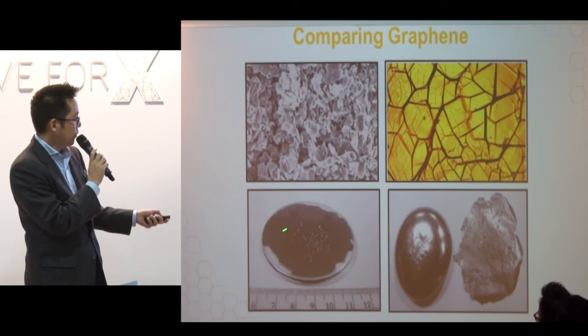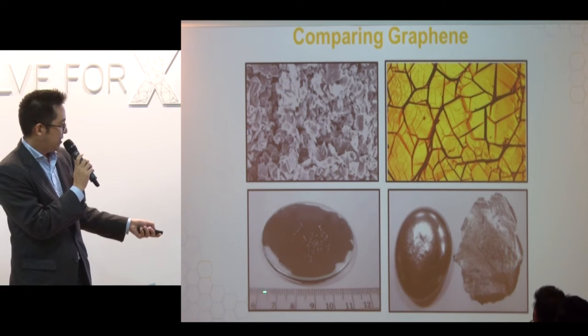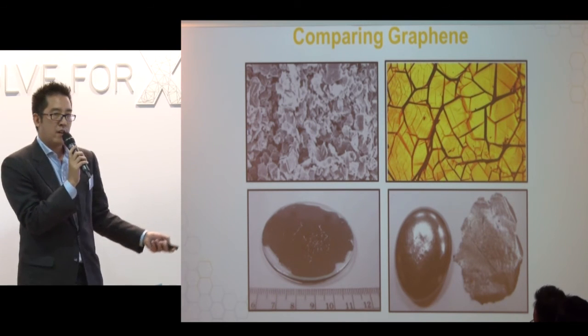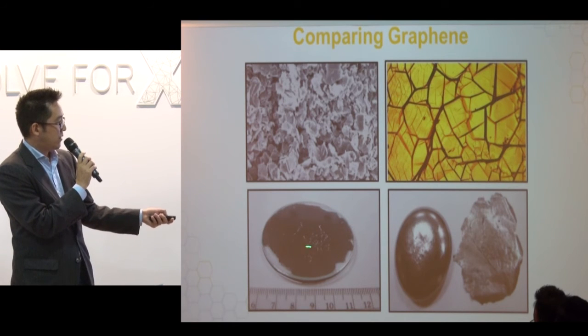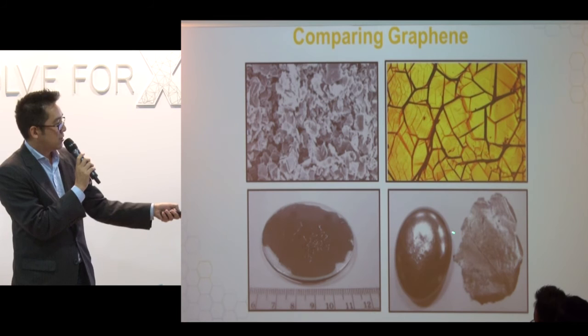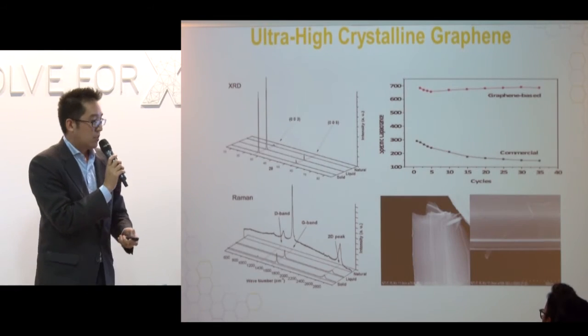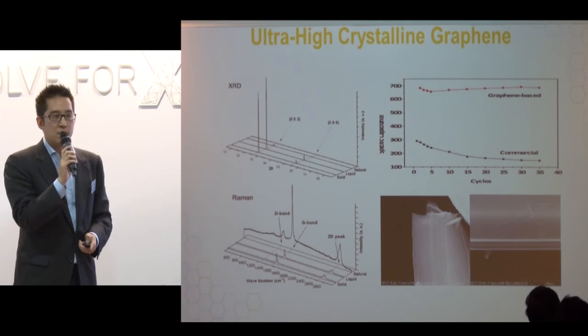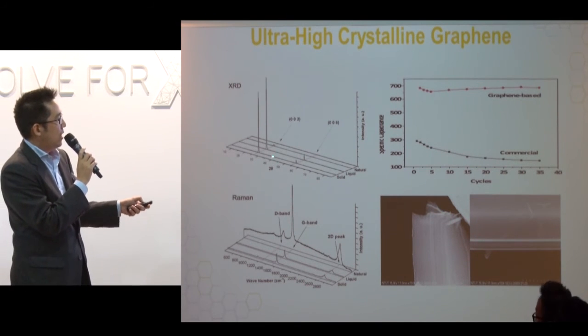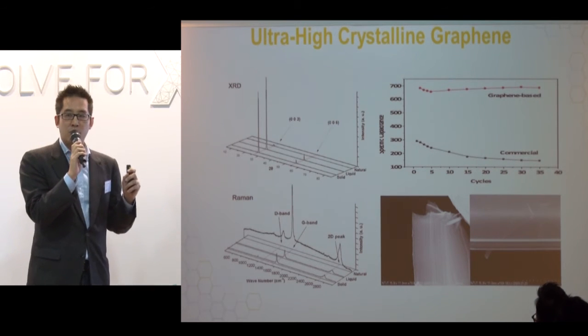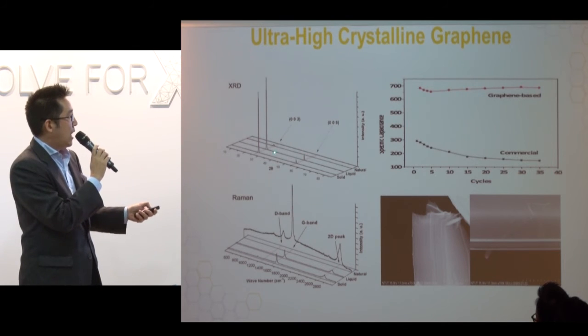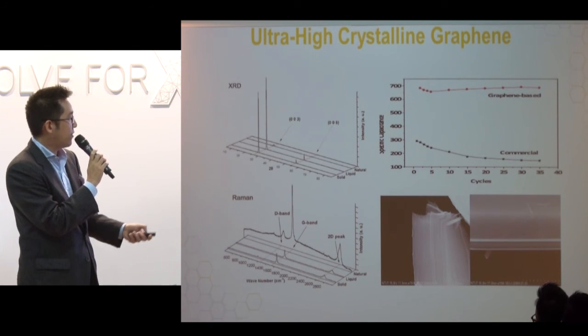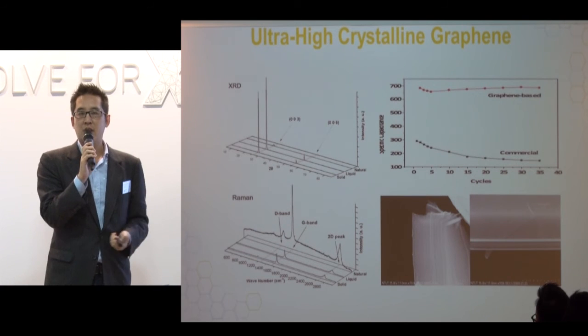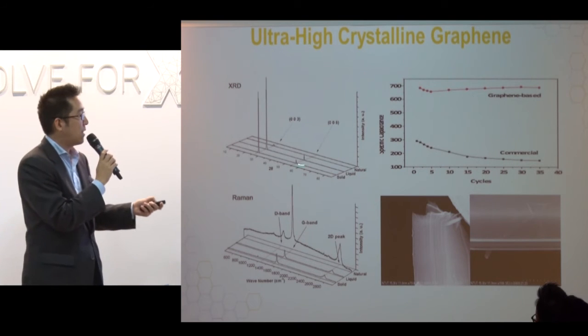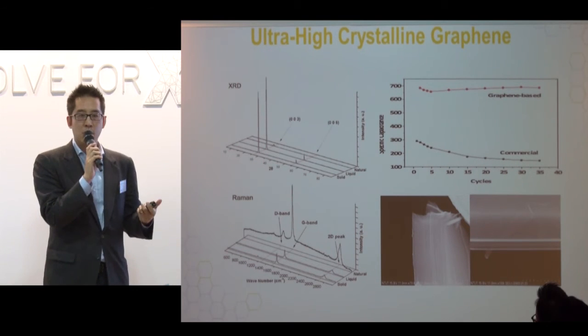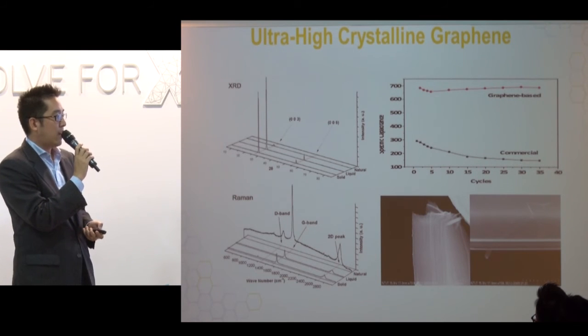You can see this is what comes out of the crucible. These are centimeters here. It's just thousands of layers of single crystalline graphene across the surface. If we use some acids to delaminate this, you see the flake right there. We've done plenty of research to demonstrate that this graphene is good stuff. Here we compared very high purity natural graphite, the best you can get on the market. If we do X-ray diffraction or Raman spectra, the size of the peak indicates the quality or crystallinity of graphene. You can see that our graphene is through the roof. The order across centimeters of area is quite extreme.